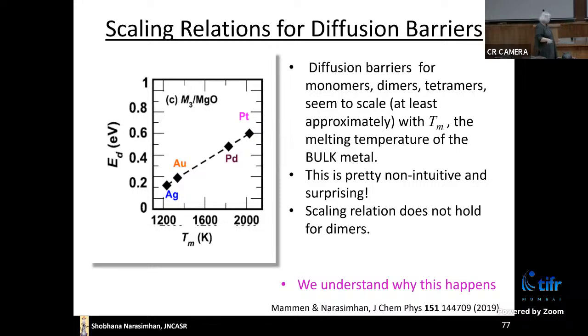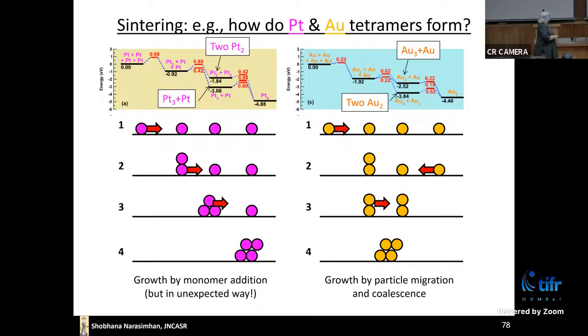Okay. And then from this, we can also study the processes by which this sintering happens, because we have the diffusion barriers, etc. And we find the process is different for different metals. I'll just show you this one, okay? We find that if you want to take 4 platinum atoms, single atoms, and sinter them into a tetramer, a 4-atom nanoparticle, it happens with addition of 1 atom at a time. It's called monomer addition, which is what you'd expect. But people always thought monomer addition means you have a larger nanoparticle, 1 atom diffuses along, comes and joins it. But what we found is the opposite is happening. The 1 atom is staying stationary and the larger nanoparticle is moving and joining it.